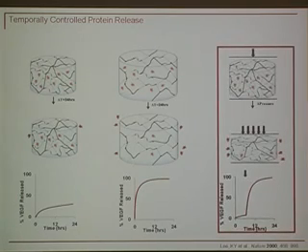We were interested in a bit of an alternative phenomenon. So the other thing that's been borne out in the literature a bit from Dave Mooney's group and others is that if you apply a mechanical strain to a hydrogel that contains a protein drug, then it's possible to perturb that network so that protein essentially gets released. And this has to do with changes in interaction between the protein drug and the background network, as well as changes in convective flow of fluid in the network.